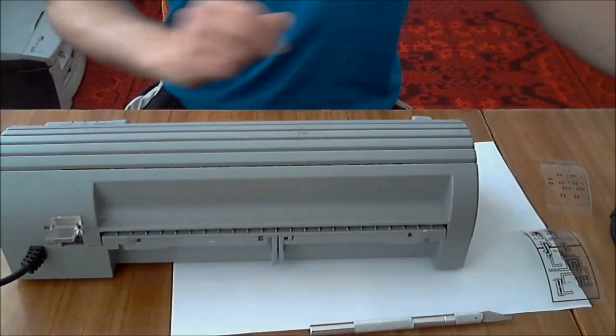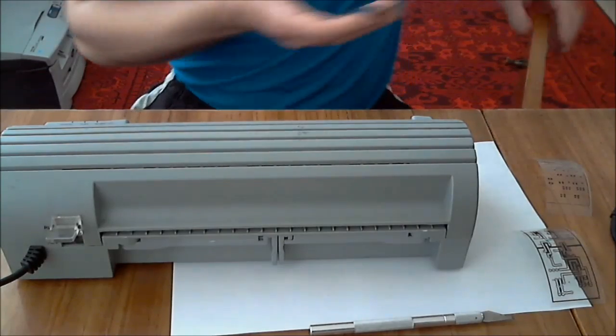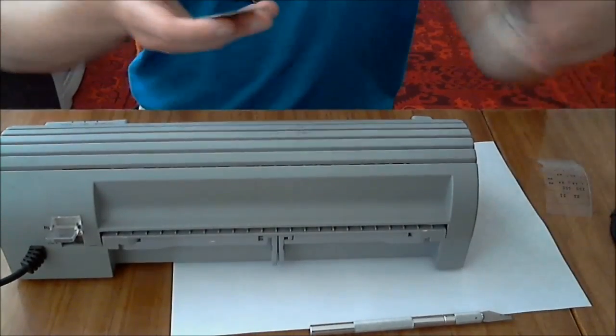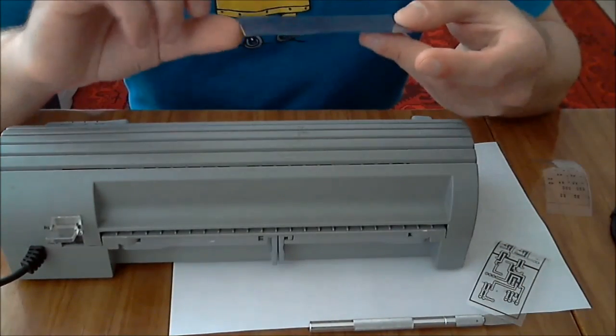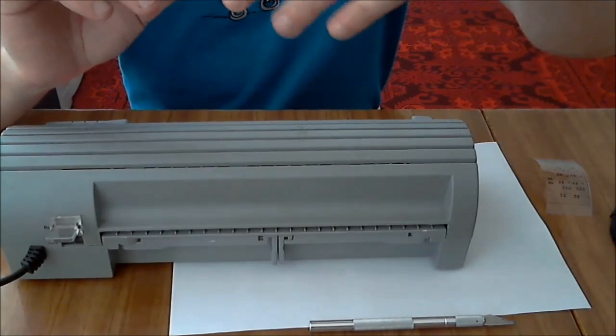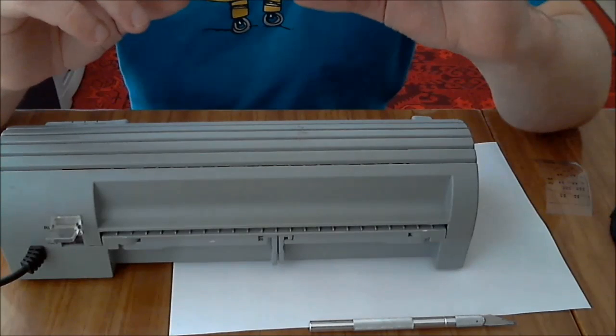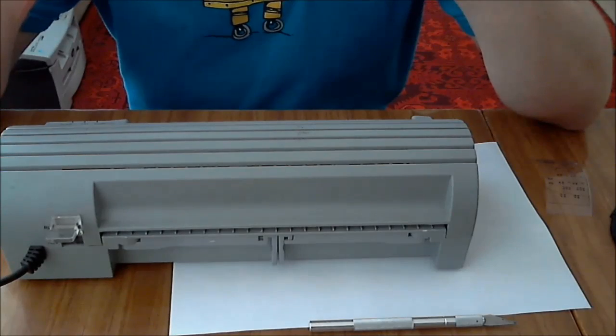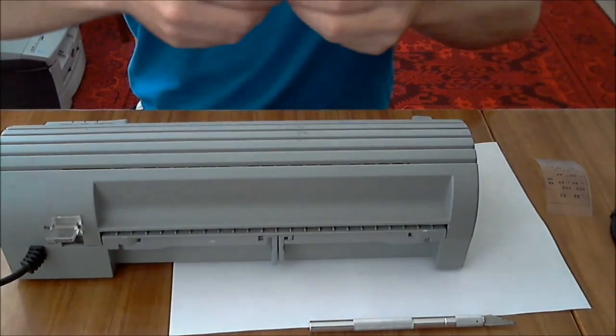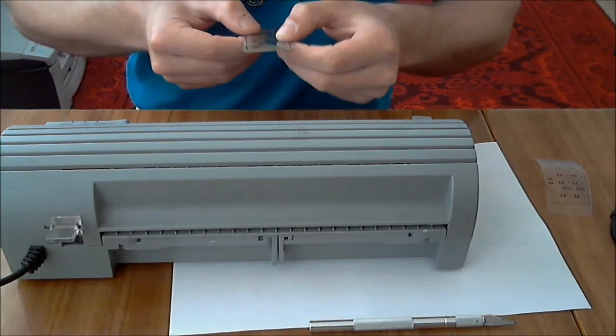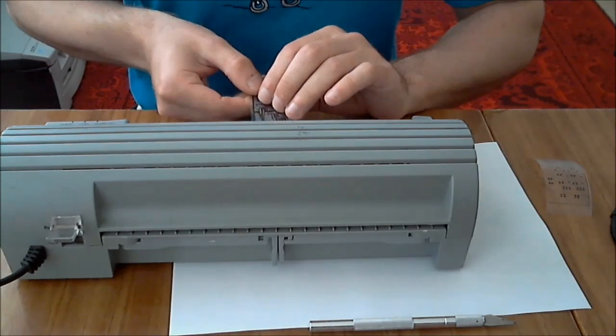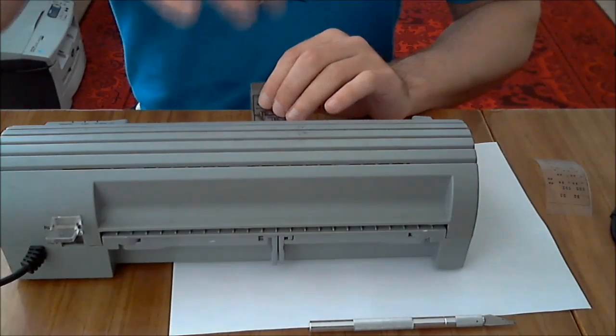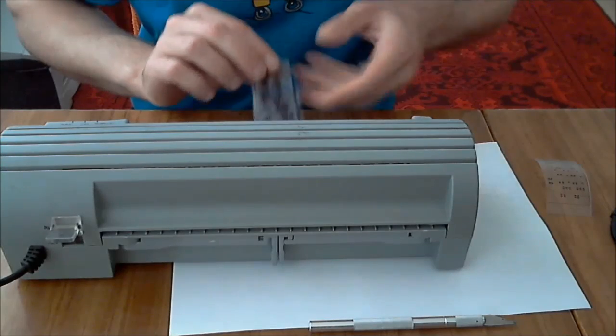The laminator is hot. We can get our PCB back out. And it's time to put a photo mask on it. So what most people do is they build a frame with two glass plates and press the photo mask with the PCB between those two glass plates. But what I found out is that you can use this same laminator and just stick your photo mask right on the PCB, right on top of photoresist, toner down. And it works just as good. Actually, it works better because this way you don't get all the UV blockage from glass itself.